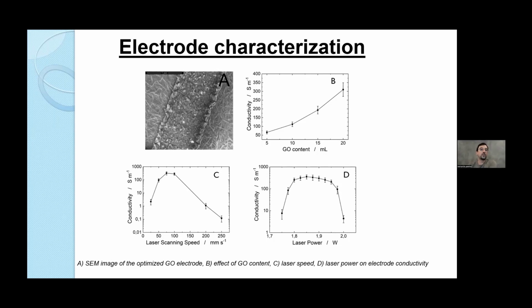After this optimization, we have studied the effect of laser scanning speed and laser power, shown in images C and D. And as it's possible to see, these two parameters have a very high impact on the electrode conductivity. Particularly in the case of scanning speed, we need a scanning speed that is not too fast, but not too slow, because then the support would be burned. The optimum scanning speed was found to be 75 millimeters per second. In terms of laser power, we have a plateau between 1.8 and 1.9 watt, and we have chosen 1.85 watt as the optimum one.